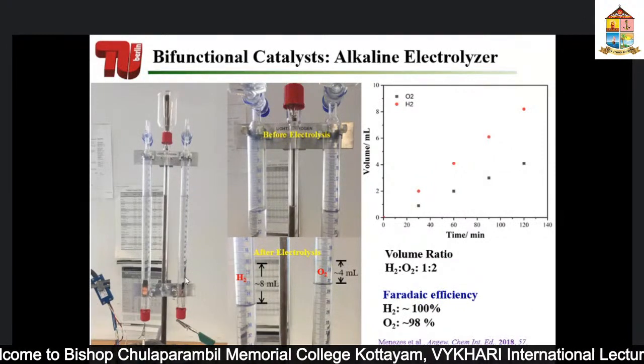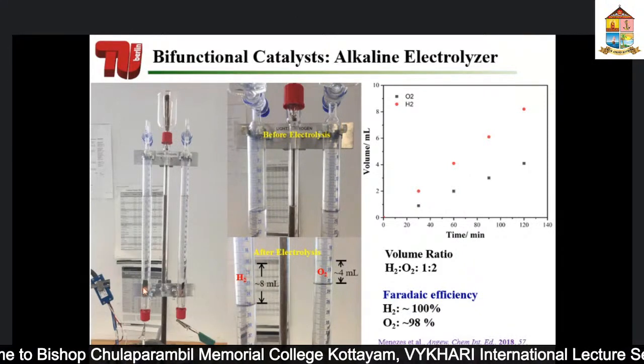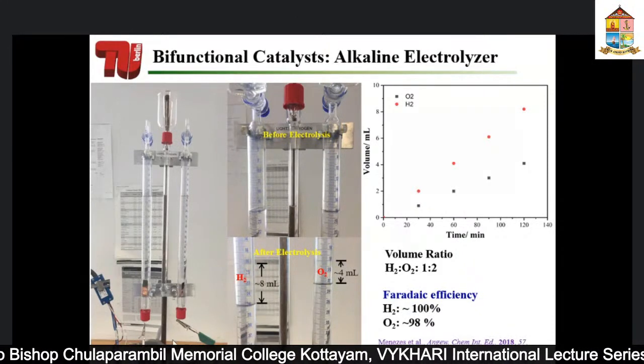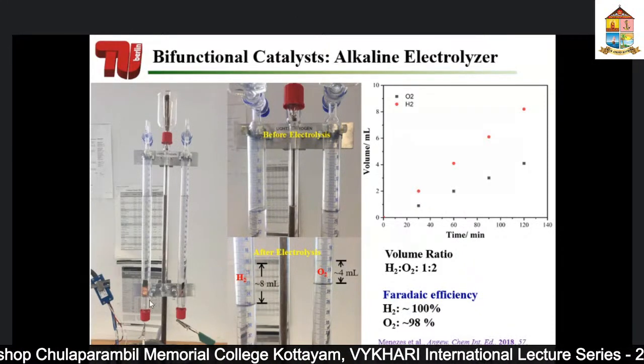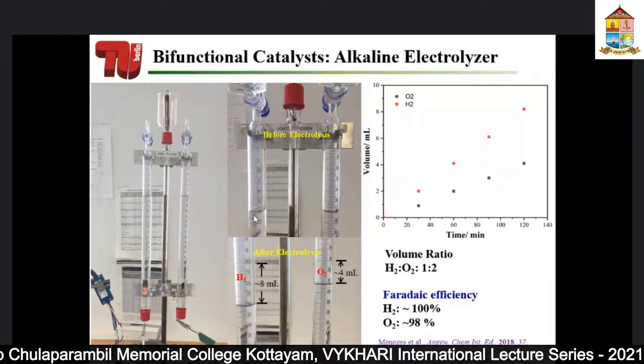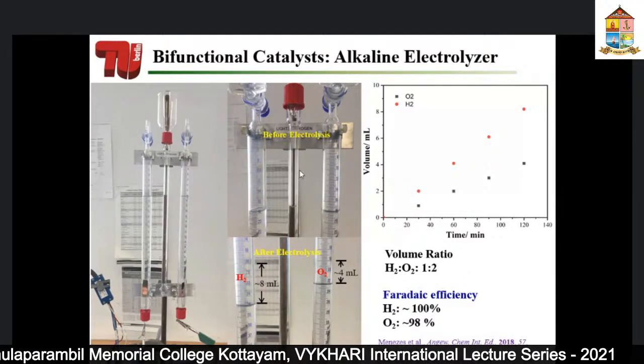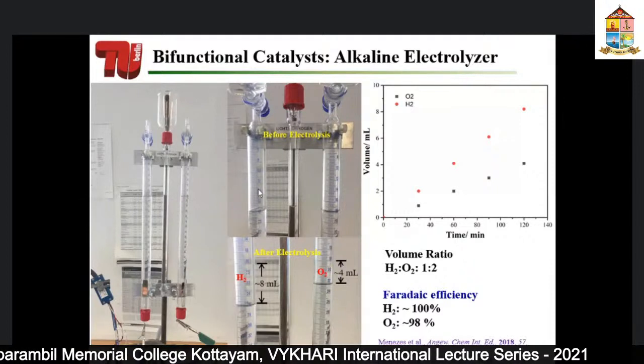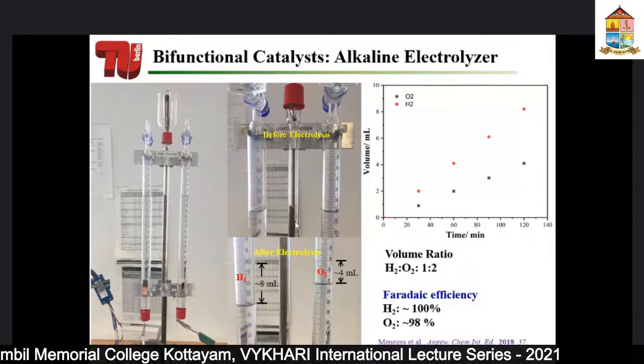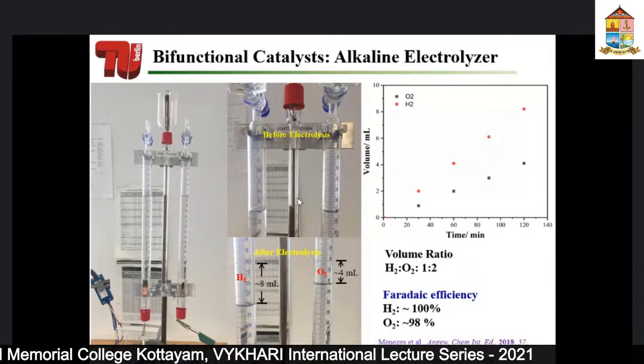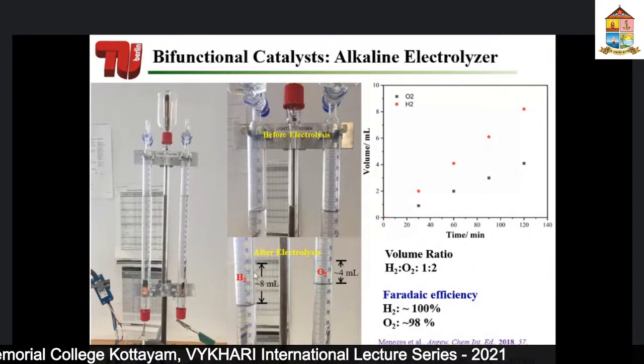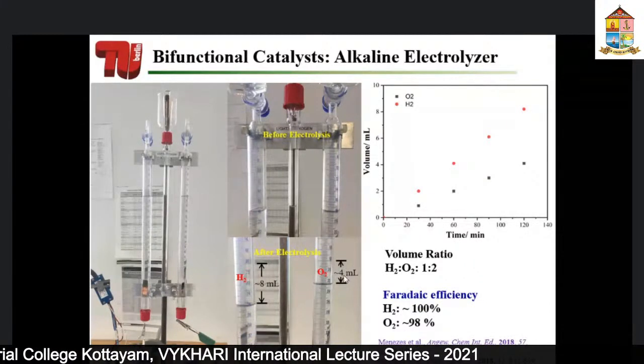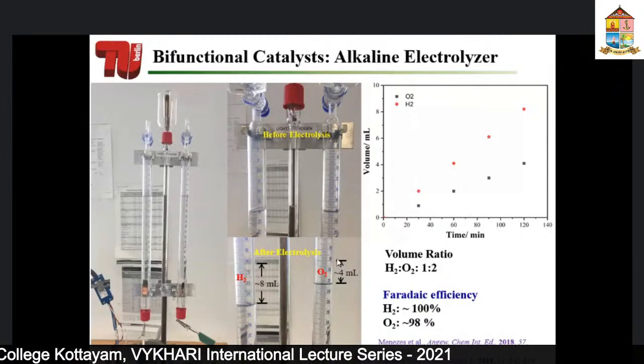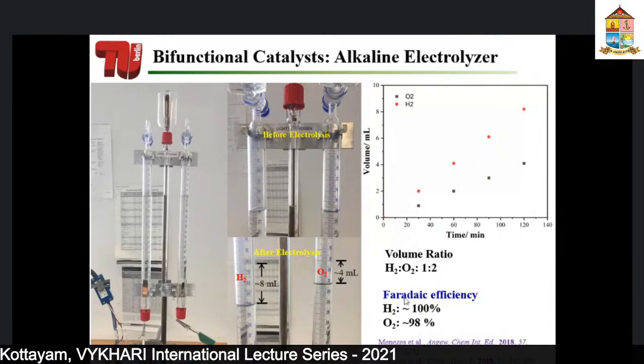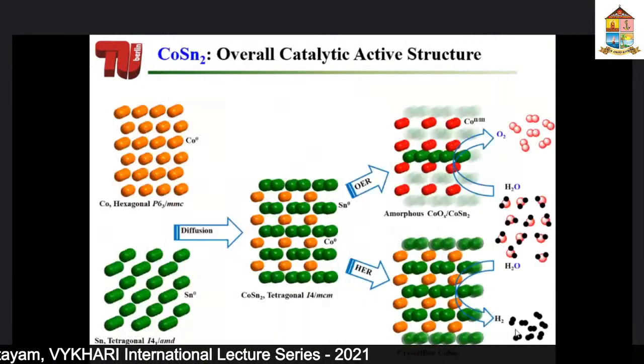If you're interested, you can always construct some kind of alkaline electrolyzer in your own laboratory. So this is something like a pressure cell. You can connect your electrodes to the potentiostat and apply potential, and you could see when the gases are releasing, because the pressure decreases, the water level comes, or the electrolyte goes up here, and then you have this difference in gases, so that you see that if you get 8 ml of hydrogen, you always get 4 ml of oxygen. So this means our efficiency is almost close to 100%.